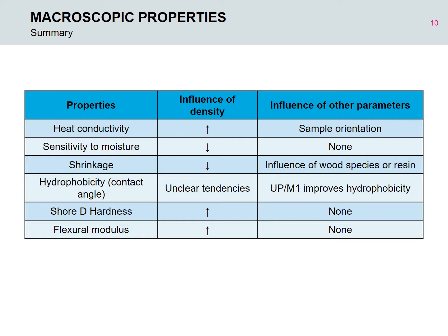We have also noted the influence of some other parameters depending on the considered properties, like sample orientation, wood species, or resin. For example, one of the resins containing the phosphorus monomer M1 improves the hydrophobicity.